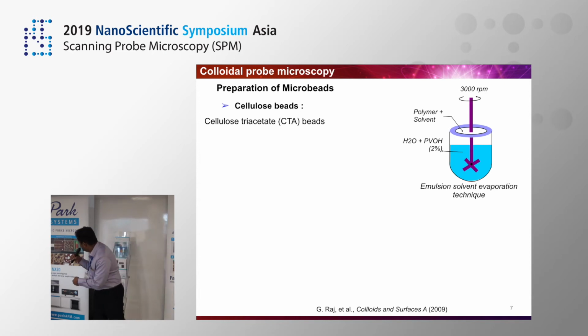So here is the preparation of the microbeads. In this case, we start with cellulose beads. Cellulose is a very difficult polymer for processing. It is highly crystalline. So we start with cellulose triacetate beads. We dissolve the cellulose triacetate in a solvent, and then we disperse it in polyvinyl alcohol, 2% in water, with high stirring. Once we introduce the polymer solution, what happens is an emulsion solvent evaporation process, which results in giving this cellulose microbead material.